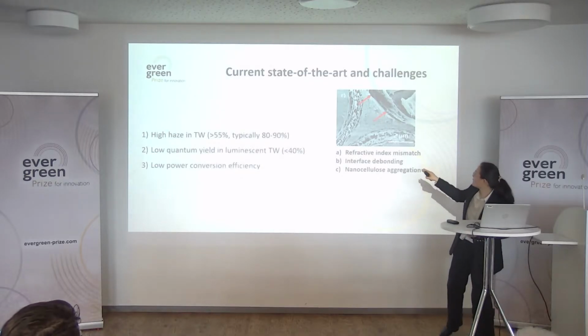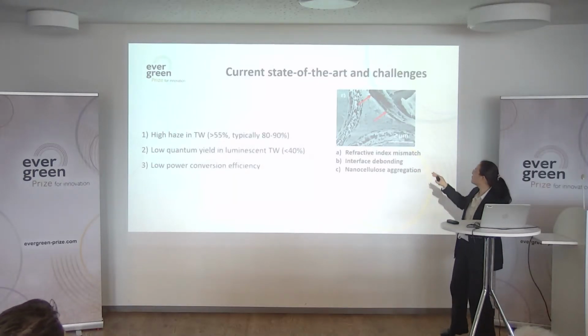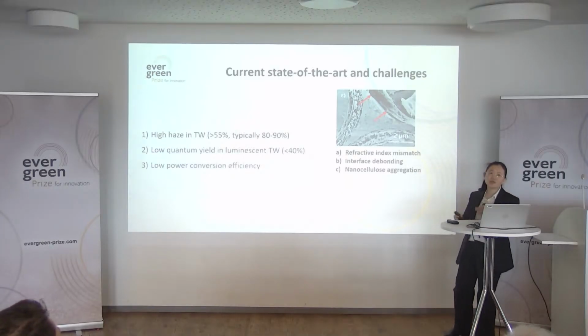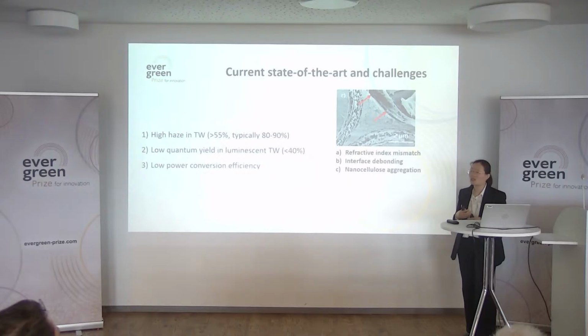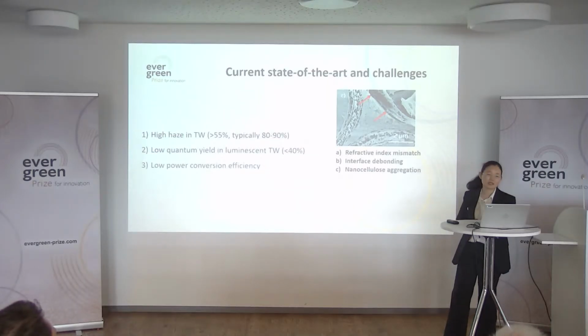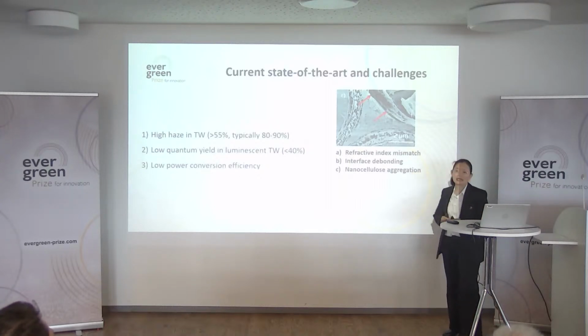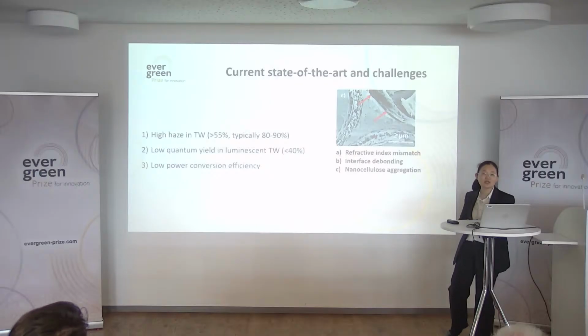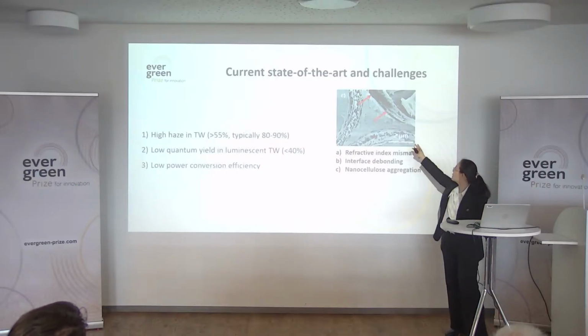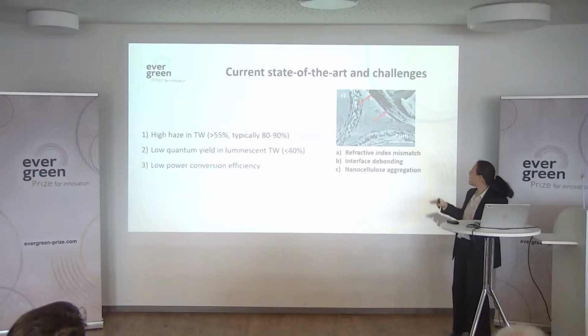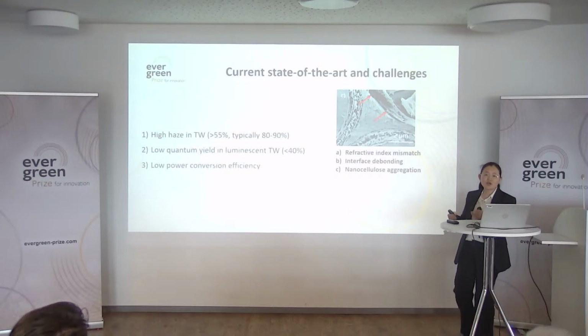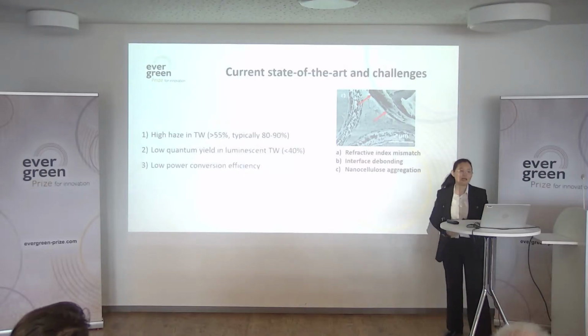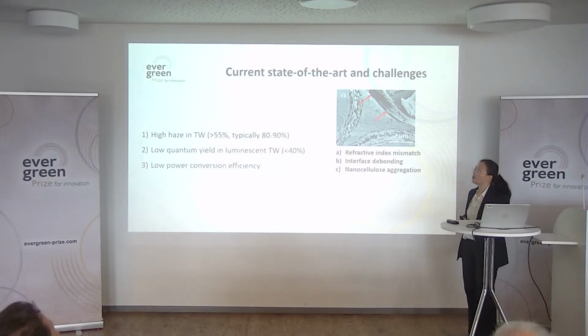So we previously already knew that the high haze is mainly from the refractive index mismatch between the infiltrating polymer and the wood scaffold. The second is the interface debonding generated during the polymer curing process. Another one that is normally neglected, and that we found recently is really critical for the high haze, is the nanocellulose aggregation in the cell wall. So our goal is to further decrease the nanocellulose aggregation in the cell wall. From previously native wood that could be up to 100 nanometers, we want to decrease it to less than 20 nanometers. So this is also the focus of this project.